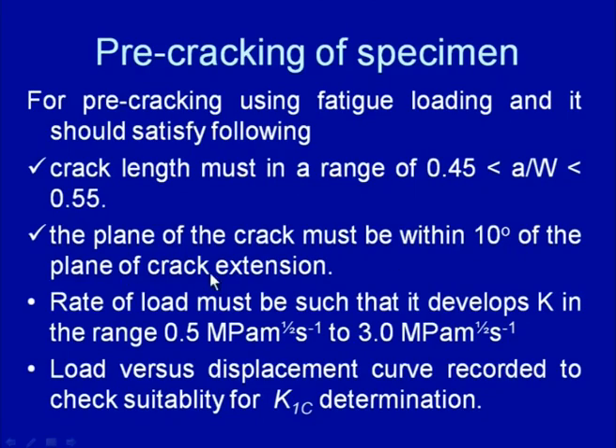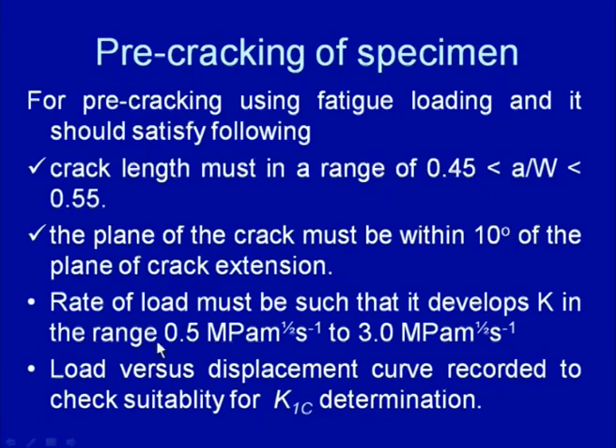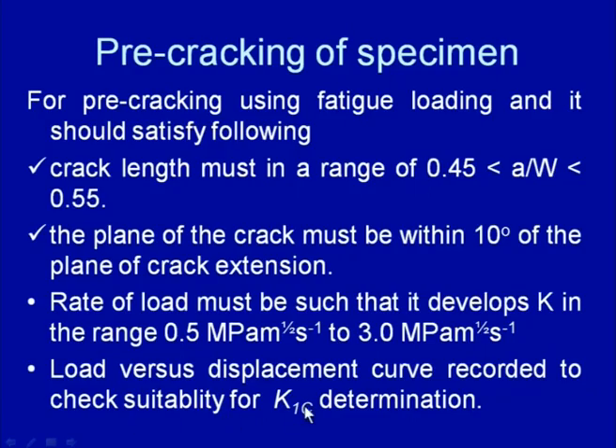A is the crack length, and we have already defined these A and W parameters. The plane of the crack must be within 10 degrees of the plane of crack extension, and the rate of load must be such that it develops the K, that is the stress intensity factor, while increasing the load, in the range of 0.5 MPa square root of meter per second to 3 MPa square root of meter per second. The load versus displacement curve is recorded to check the suitability for determination of the K1C.